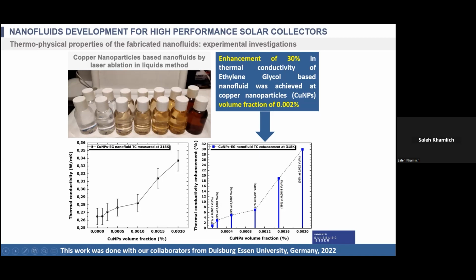So by looking at these figures, at different concentrations or volume fractions, here is 0, which means pure ethylene glycol. By increasing the volume fraction to 0.002, the thermal conductivity is going up. We didn't want to work above that because we have done that previously, and it's not our interest. Our interest is to come up with nanofluids with the lowest possible volume fraction. As I mentioned, our Mother Earth has limited resources, and we have to make sure to use our resources wisely, in order to use them for different applications and to come up with new technologies and so on.